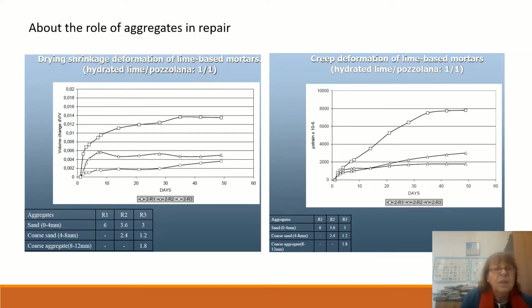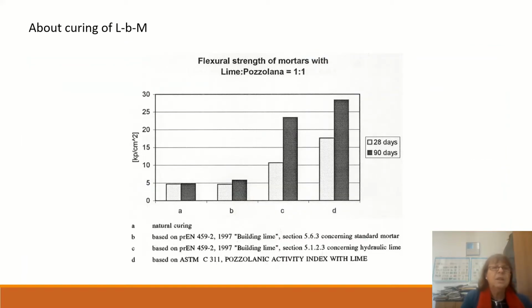About the role of aggregates, we can say that the use of coarser aggregates, especially in the case of thick joints, mitigates the drying shrinkage and creep deformations, but in any case these deformations in lime-based mortar are much higher than in cement-based mortar. The curing regime plays an important role. If a lime-pozzolan binding system is cured in a natural curing system or without any moisture, then the level of strength is very low, while if it is properly cured in moisture, then we have adequate strength development at 28 and 90 days.